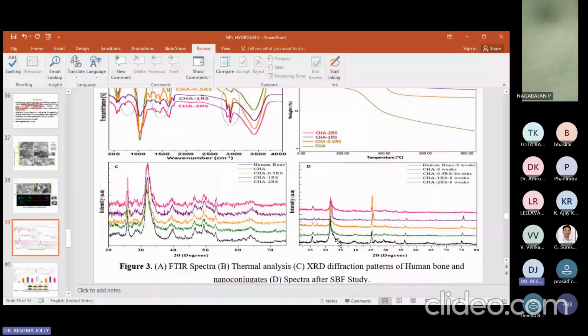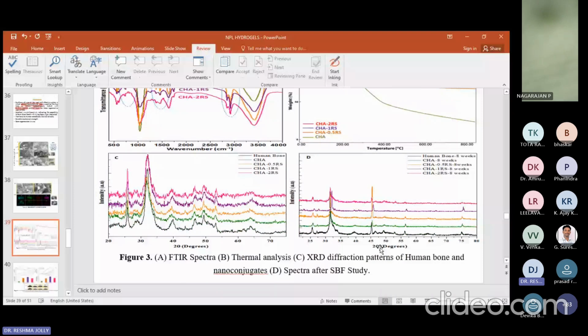And this is the SBF study spectra. We incubated for 4 weeks and 8 weeks, and then we took the XRD. So this is before the SBF study, and this is after the SBF study. And here we found the peaks got strengthened very much because of the apatite formation. So this is the apatite formation that actually happened, which gave this difference.